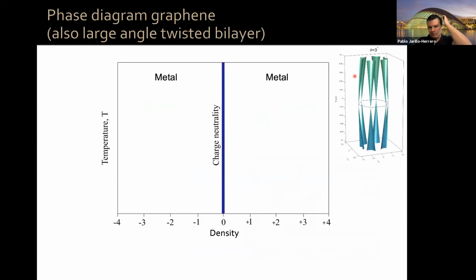Now, I want to go back to the phase diagram of graphene, okay? And then we'll slowly build towards it. So if you have graphene, you have Dirac cones. Also, if you have large angle twisted bilayer graphene, okay, you have Dirac cones. This is an electronic structure for 3 degrees twist angle. As you can see, at low energies, it just looks like graphene. In a phase diagram, temperature versus density, there's only one relevant, interesting region, which is the charge neutrality point.